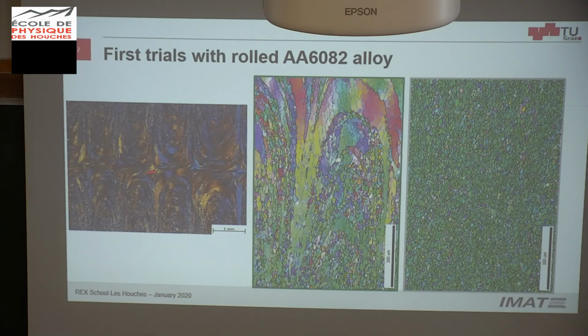You can see, by increasing the strain, that the strain in the middle should be 0. In this case it's not, because the sample was not really aligned, but it must be 0. Then we increase the strain in this direction. But due to the texture of the material, we got this and some misalignment. We also got this very strange pattern. We can also see the evolution of the dynamic recovery, continuously transforming into high angle grain boundaries. And everything is green, which means we have a very large texture. We produced a textured material.